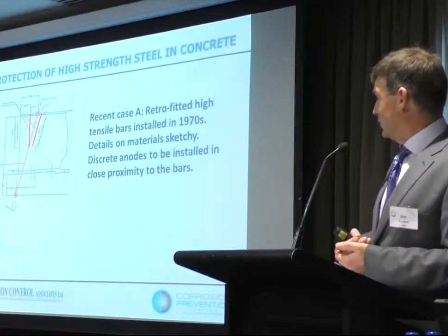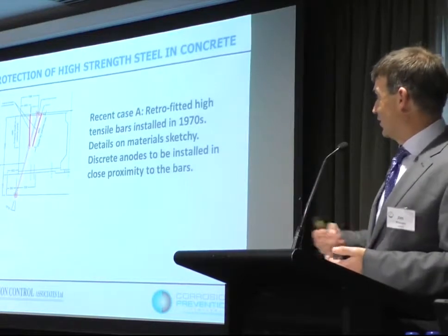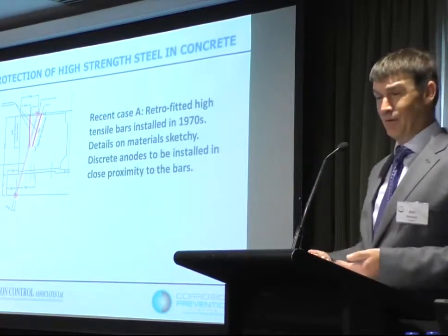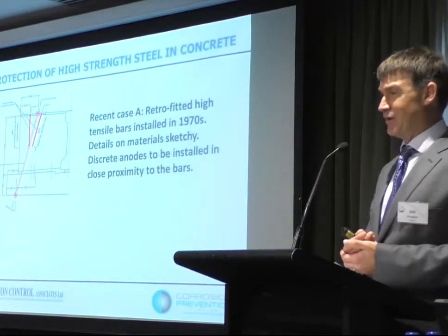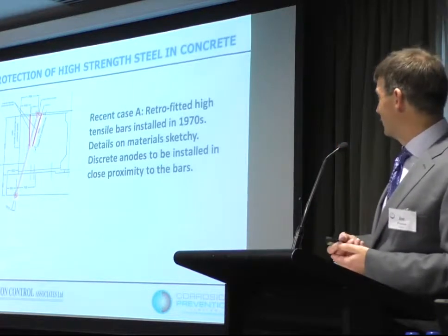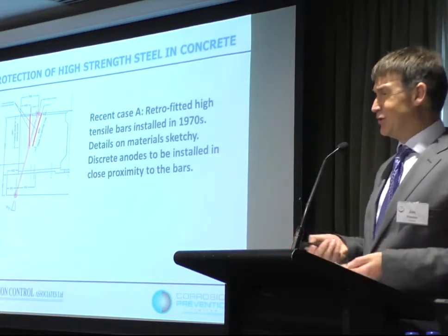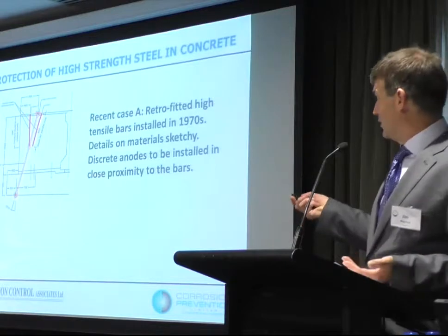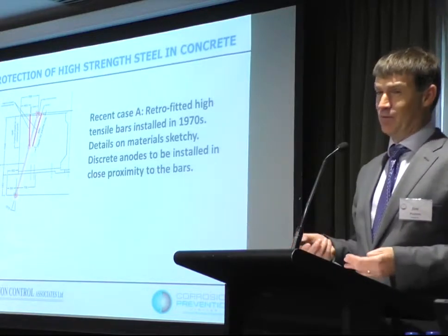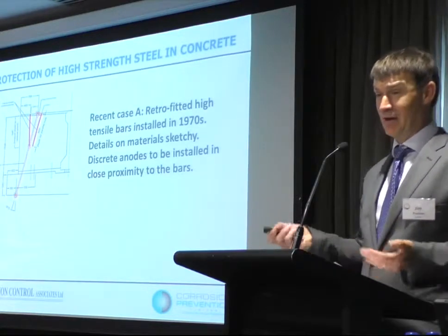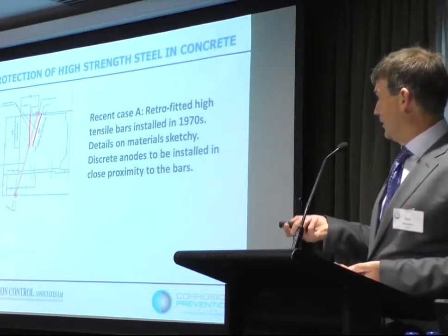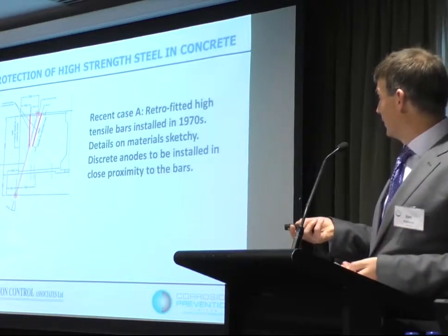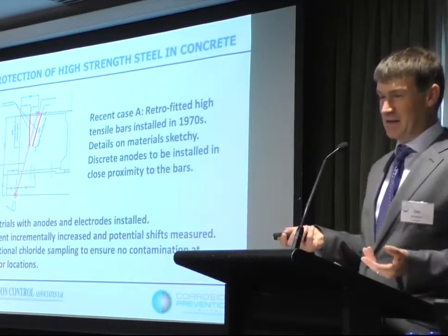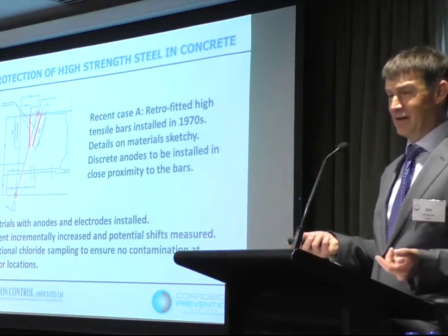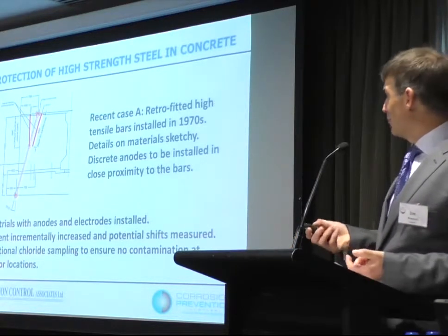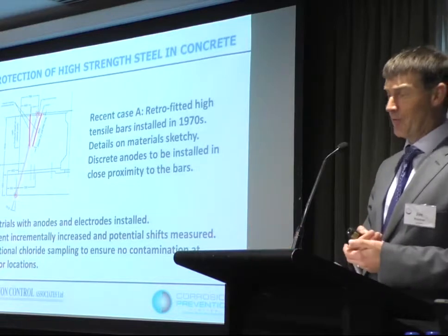We wanted to provide corrosion protection, cathodic protection, to the reinforcement on the soffit. That involved drilling long discrete anodes past these bars, so it's a concern that we may get these bars to too negative a potential. The only way to see what was actually going on was to install a full-scale site trial, install anodes, install reference electrodes as deep as we can next to where the bars were, and slowly switch the system on incrementally and make sure that the potentials we were measuring weren't getting anywhere close to where we thought we may have a problem.